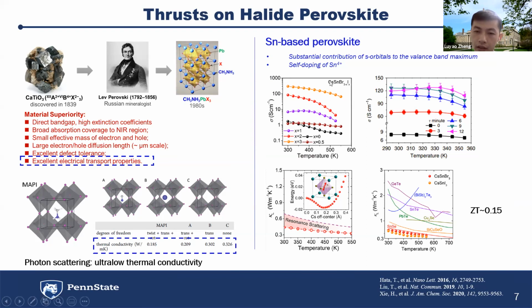So as shown here, this is a tin-based perovskite. So the electrical conductivity is relatively higher than the lead-based perovskite, as I mentioned. For the lead, it's only about 10 to the minus 3. So here we can get almost over 100. And when we put this material in the air, there is oxygen. So for a certain time, it will be oxidized, inducing some self-doping, resulting in an increase of the electrical conductivity.